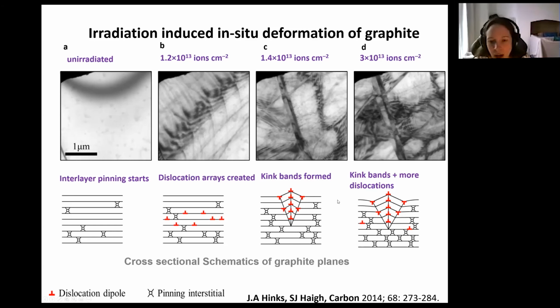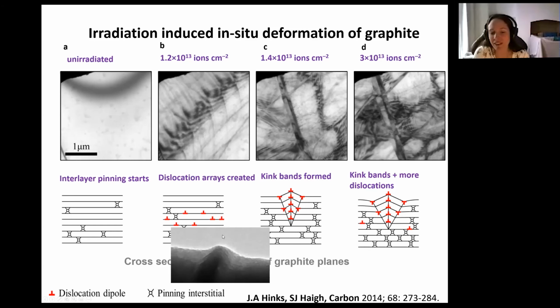Okay, and if you tilt the crystal, you can actually see that these types of crystal defects really are sitting out of the plane. So that's this line, but tilted to the side and at the edge of the crystal, so you can really see that it's a 3D feature within the specimen.